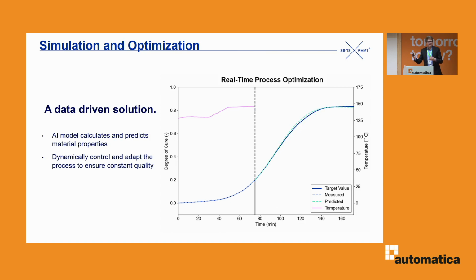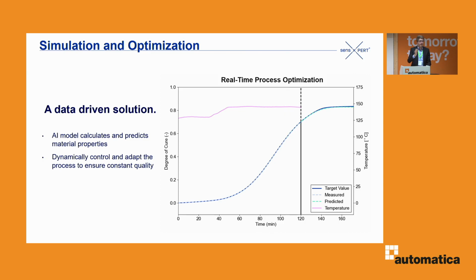And what you can see here is that about one third into the production process, we can basically predict what the outcome is going to be, right? In the beginning, it's shifting back and forth a little bit. But once we are about one third of the cycle time into the process, we can predict what happens in really good quality and basically know beforehand when the part is going to be finished, when it's going to be good, and when we can demold and end the cycle.